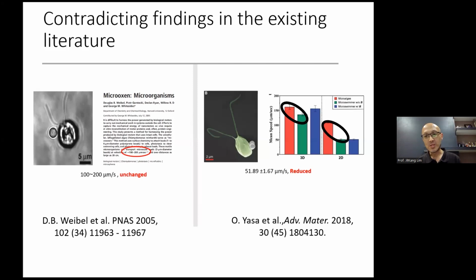And surprisingly, when we first look at it, we thought it's a non-surprise. It's not a very surprising result because of many reasons. But when we dig further into the literature review, there are so many people who have made this kind of observation. However, by different groups of people, all from top universities. For example, here there's a group from Harvard Chemistry, and this group is from the Max Planck Institute of Germany.